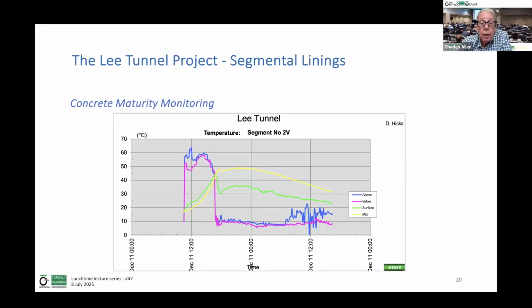So what we did, they set up on a segment. This is the segment in the carousel, and we had thermocouples at the midpoint of the segment and the actual surface of the segment, and these were above and below. So these were ambient temperatures. Obviously, the temperature above the segment in fresh air was more than the below because heat rises. And the critical thing is this temperature differential between the segment center and the surface of the segment.